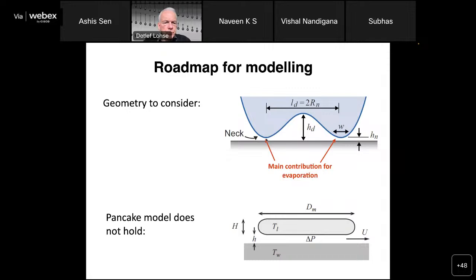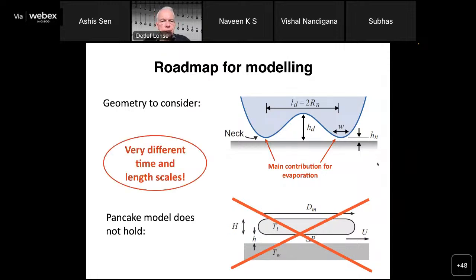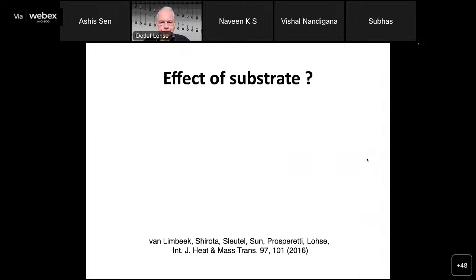And then I came up with the pancake model to somehow model the evaporation, which looked like this. But in view of these results, I must admit that this pancake model is not the greatest. And proper modeling of the heat transfer can only be done once you take this geometry here into consideration. So very different time and length scales are at play.